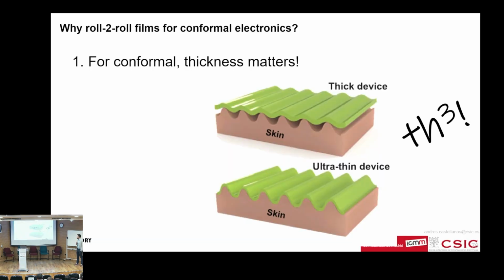First one is, of course, we are making thin films. Even if they're multi-layered with several transfers and so on, at the end of the day, these devices can be as thin as tens of nanometers thick. And the stiffness of a rectangular plate, if your continuum mechanics is a little bit rusty and you don't read Timoshenko on a regular basis, goes with the cubic power of thickness. So the thinner the device, the more compliant it is.